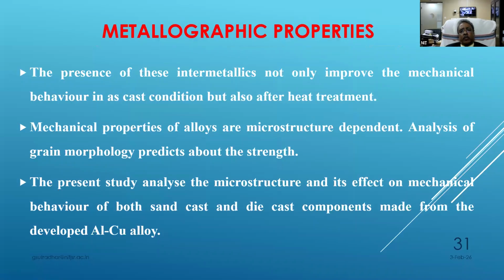Now the metallographic properties. For the metallurgical and mechanical behavior of any component, you have to see what intermetallics are present in the matrix. This study says that the presence of intermetallics not only improves the mechanical behavior, but does so in both cases, whether unheat treated or heat treated. Definitely after heat treatment, the presence of intermetallics actually helps improve the mechanical behavior.